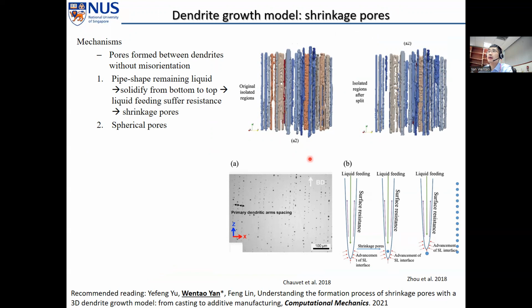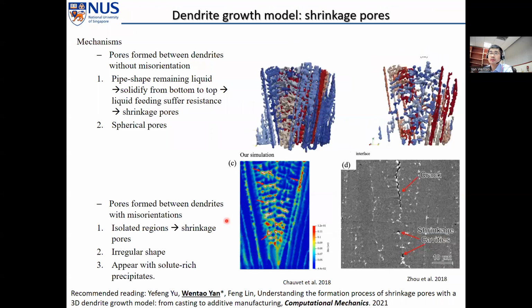So there are actually two types of formation mechanisms. One is where there is no misorientation. So all the shrinkage pores are regularly distributed and their shapes are spherical. In another scenario, there is misorientation between dendrites. So these shrinkage pores are irregular in shape, they are irregularly distributed, and they appear with solute-rich precipitates.